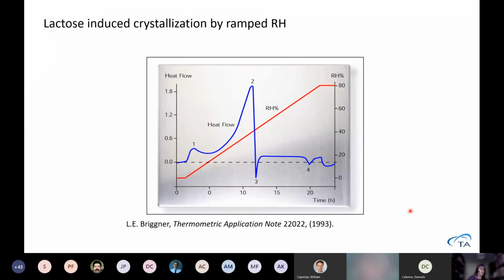We have an example here where we ramp it, from 10% relative humidity up to 80%, where we have first absorption of humidity, then we have the crystallization of the amorphous part. After it's crystalline, it doesn't want to hold water anymore, so you can see this endothermic peak is where it expels the liquid. At higher relative humidity, you have a transformation of, in this case, the lactose. This is a little more difficult to quantify, but you can detect that you have amorphous parts in your material.